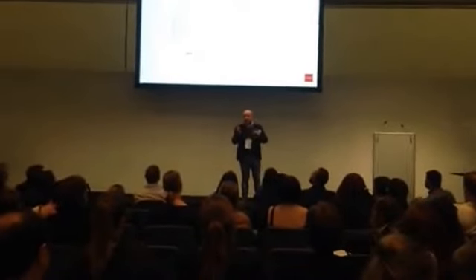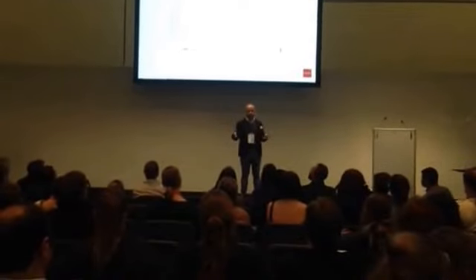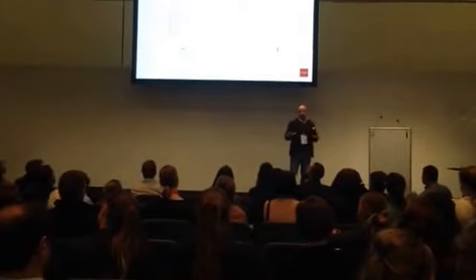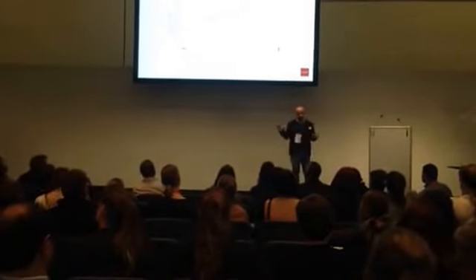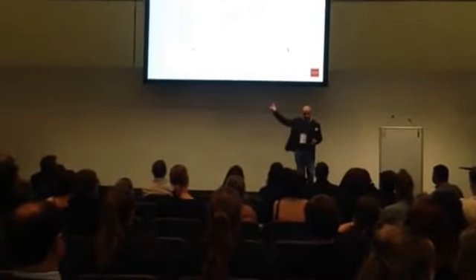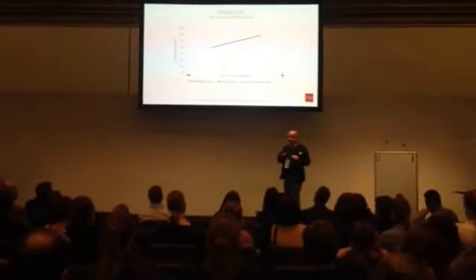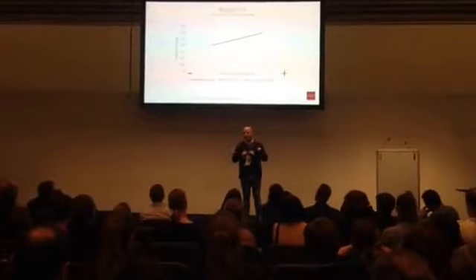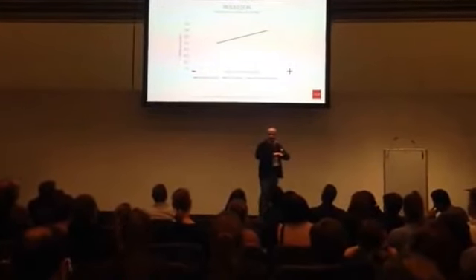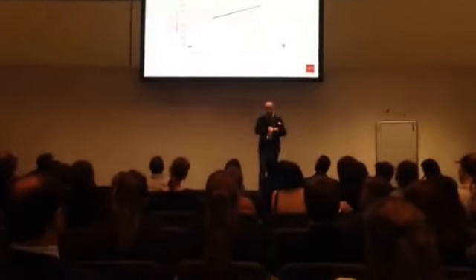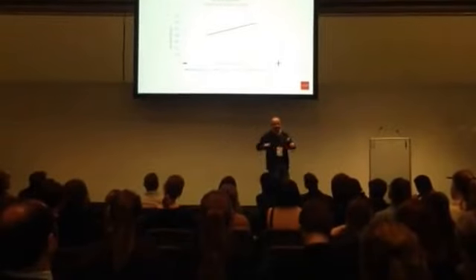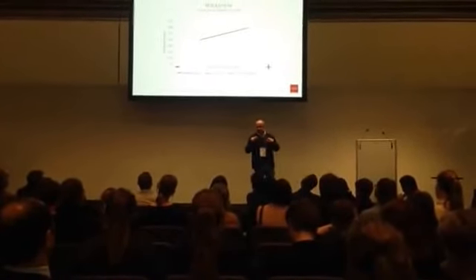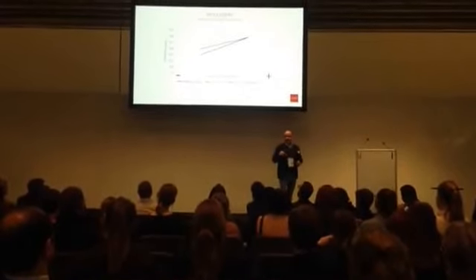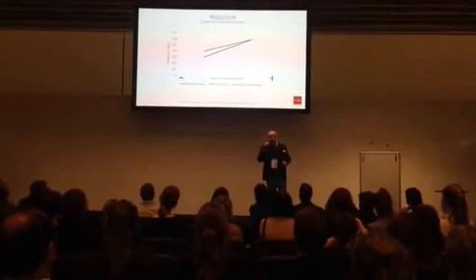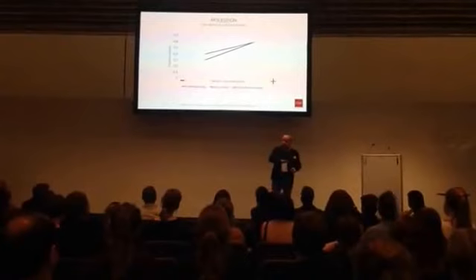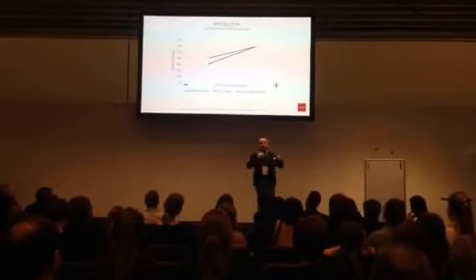There is another thing to talk about: the thickness. People ask, what is the thickness I can do with 3D printing? So I wanted to make a benchmark between 3D printing and casting. The brown line is the traditional casting. The thinnest thickness you can cast is 0.4 if you're lucky and you're able to inject the wax. But then as the surface becomes bigger, on the X-axis you see the surface dimension, the thicker the thickness must be. In the case of direct casting, because we are able to 3D print the patterns, we are also able to cast something much thinner, but then at the end, when the surface increases, we have to increase the thickness.